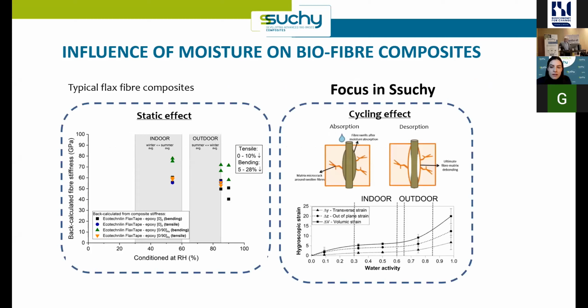So let me first talk about the effect of moisture on biofiber or natural fiber-based composites. Usually we can distinguish two effects. There's the immediate effect of the moisture, which will lower your E modulus, and in the literature you sometimes see quite drastic reductions up to 50%.